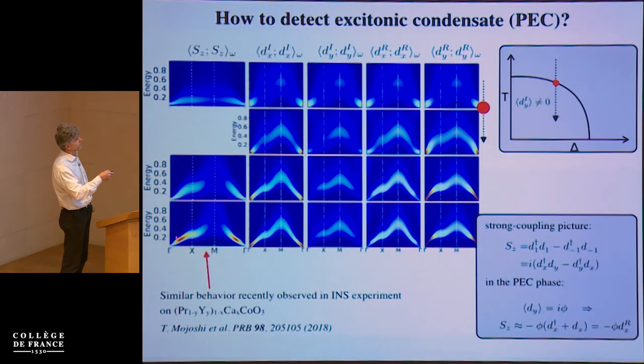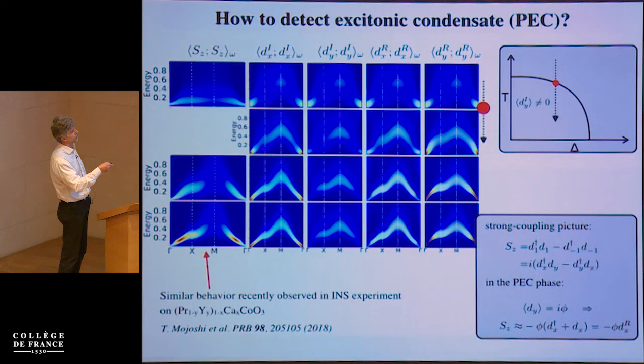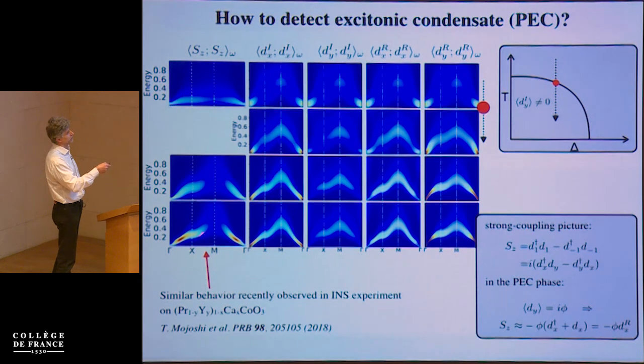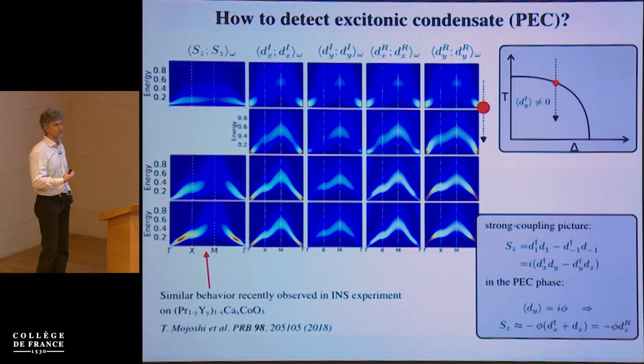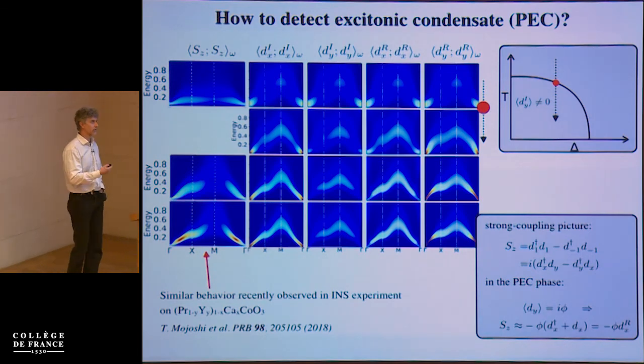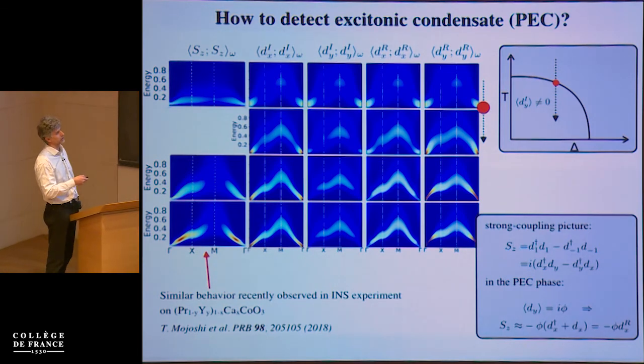If we go to the ordered phase, we see a rather sharp dispersion. Now if you compare this dispersion with the excitonic dispersions, you can see a similarity between this one and this one. And this similarity is no coincidence—it has actually a rather simple explanation.